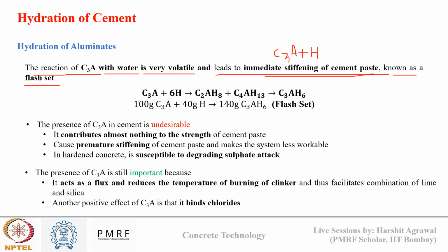How does it happen? The C3A combines with water to form C3AH6, calcium aluminate hydrate. 100 grams of C3A combines with 40 grams of water to form 140 grams of calcium aluminate hydrate. And this calcium aluminate hydrate gives rise to flash setting. As soon as I add water to cement, it will instantaneously start to set.